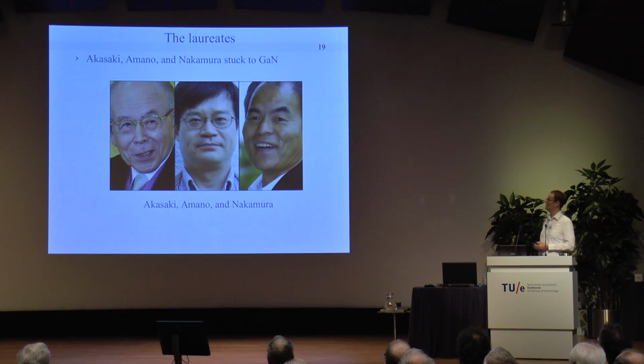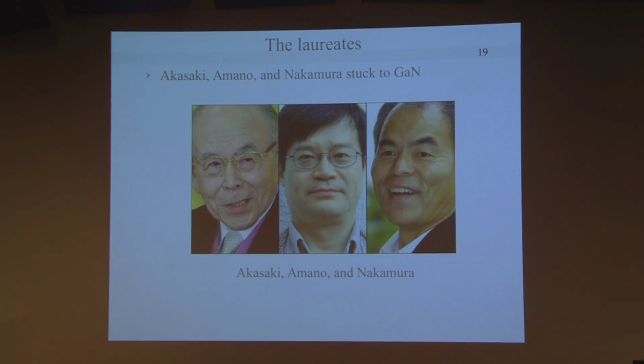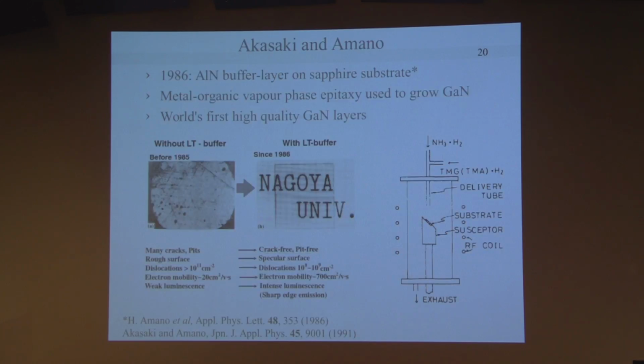So enter the laureates. These 3 gentlemen, Akasaki, Amano, and Nakamura, decided to stick to gallium nitride, and they actually solved these problems one by one. I'd like to go over some of their results. In 1986, Akasaki and Amano published a paper, here's the reference in Applied Physics Letters, where they made the world's first high-quality gallium nitride layers. What they did is they introduced a buffer layer of aluminium nitride that they first deposited on the sapphire substrate, and then the gallium nitride.